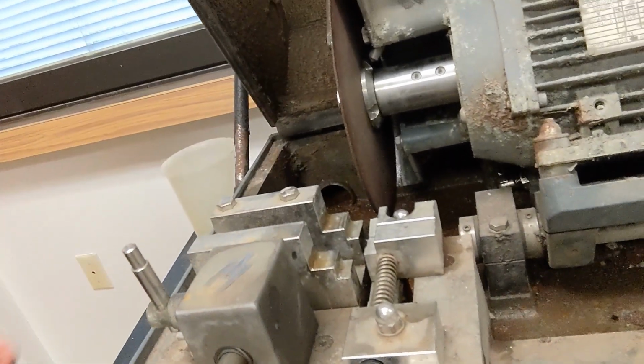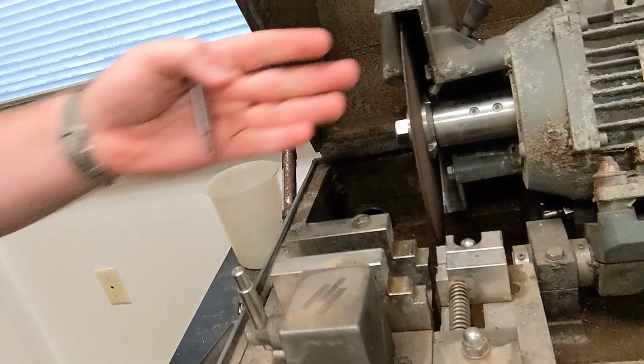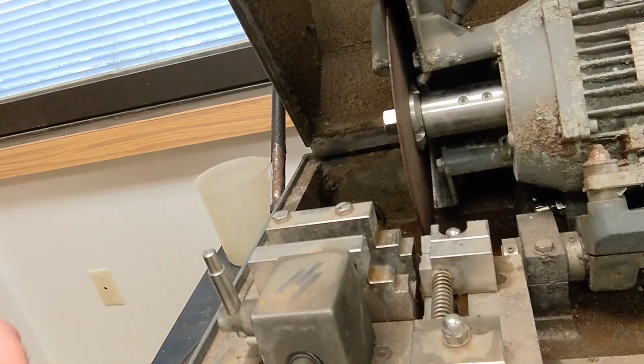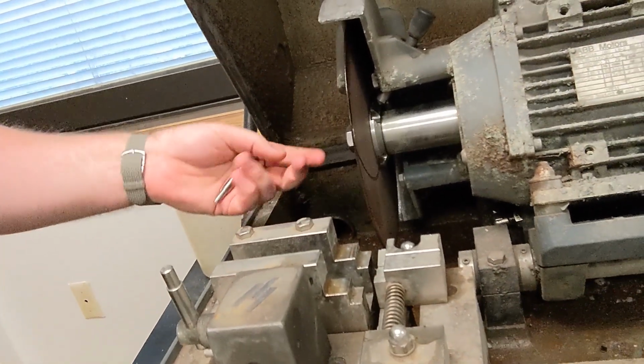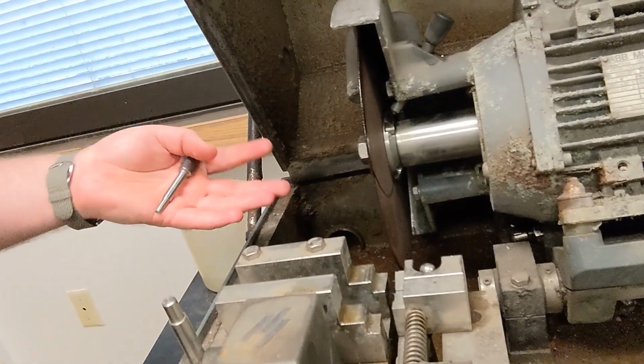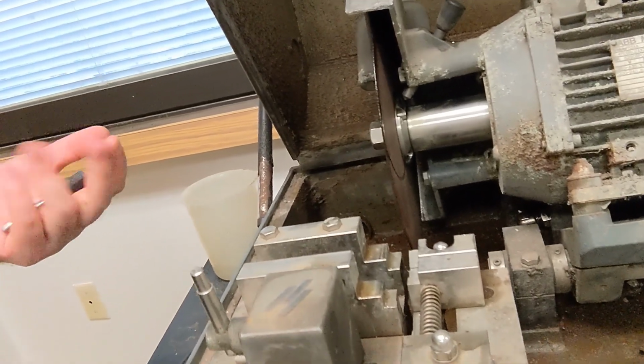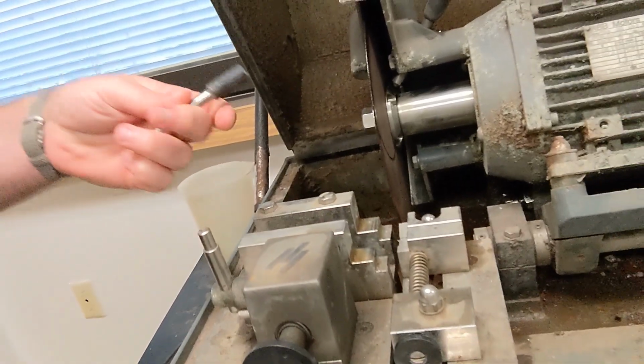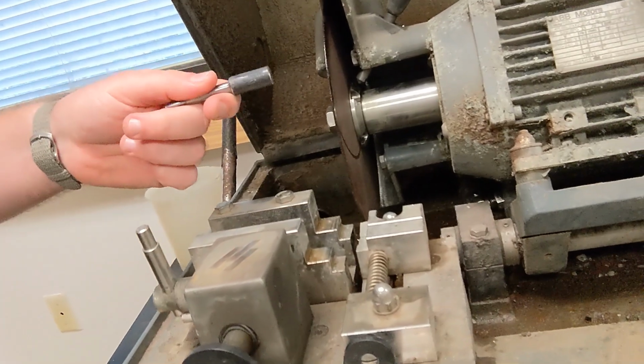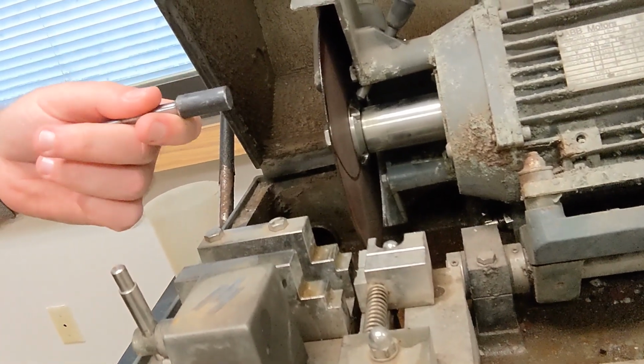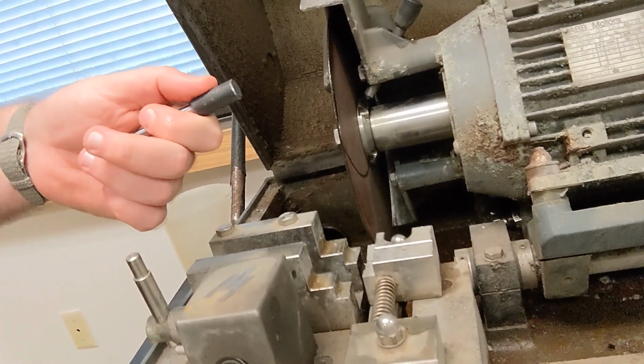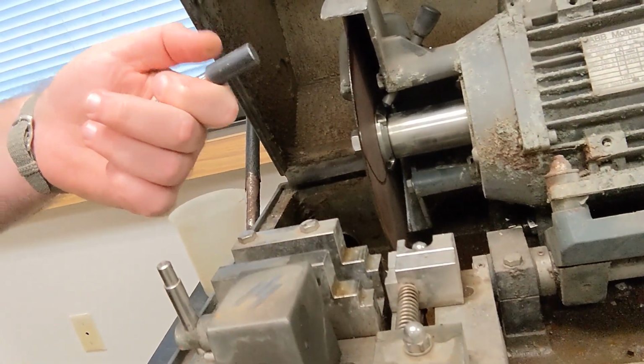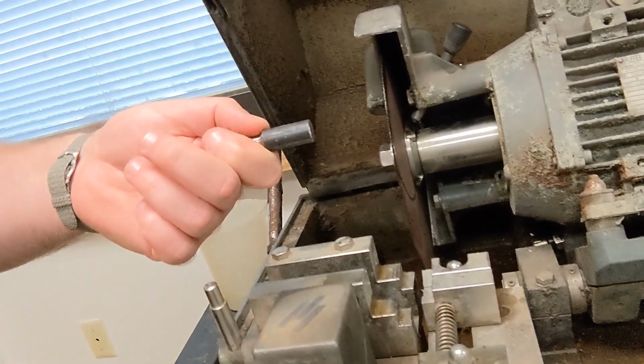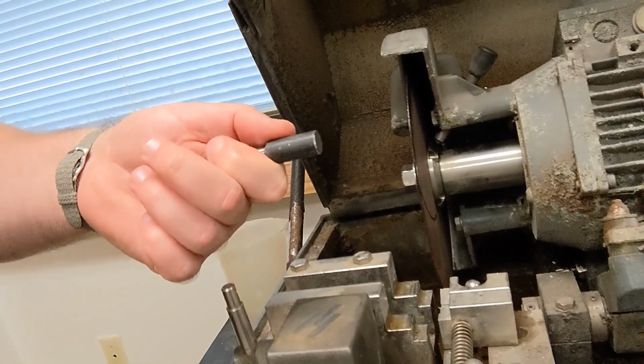We have our grips down here where we hold our sample, and this saw just slides forward and cuts through our sample. It is water cooled, otherwise this saw can heat up and explode, so we use water cooling to keep that, and also by water cooling it we make sure not to change the microstructure, because if we add heat to this bar, it's likely we will change what it was when we tested it. So heat affects the microstructure.